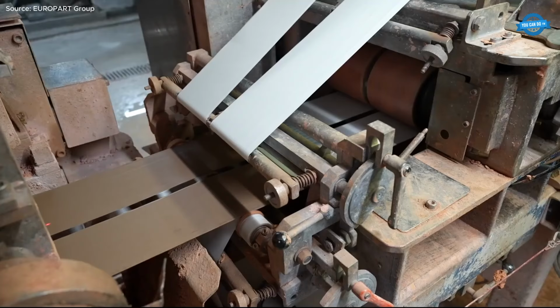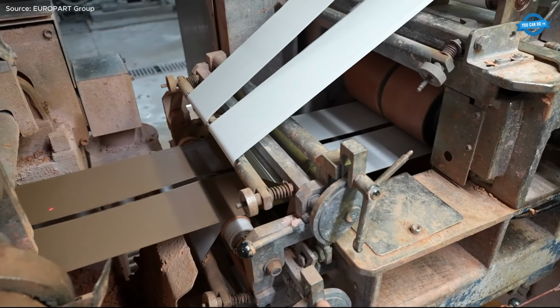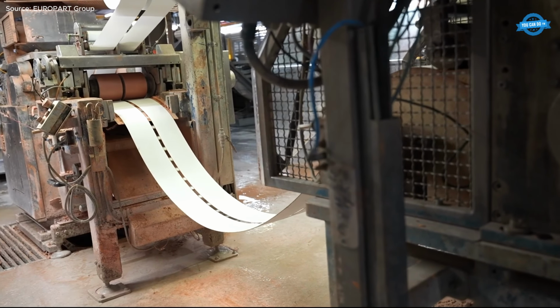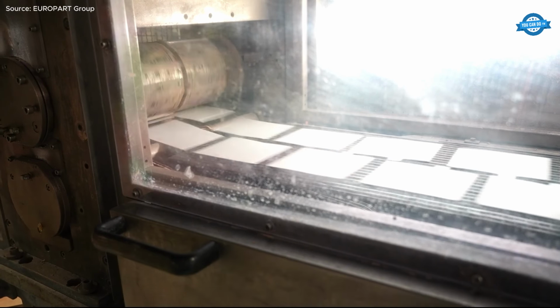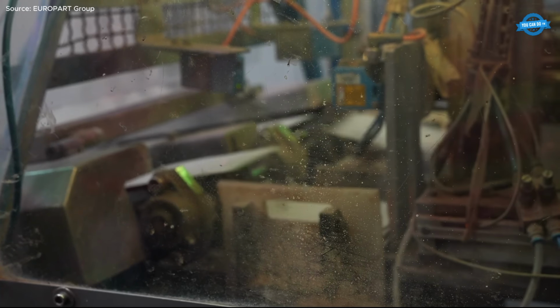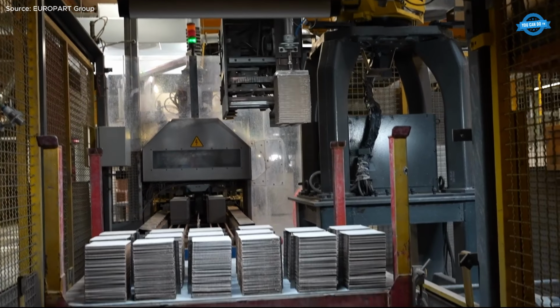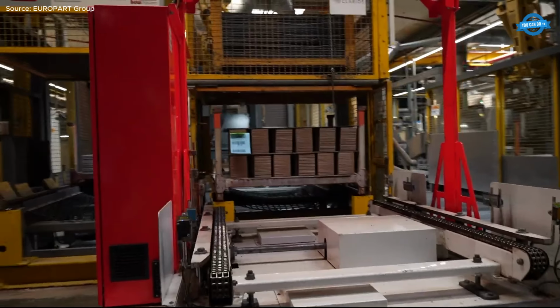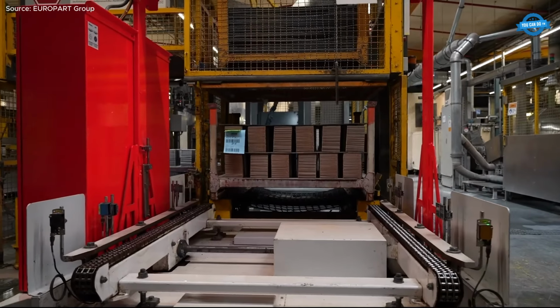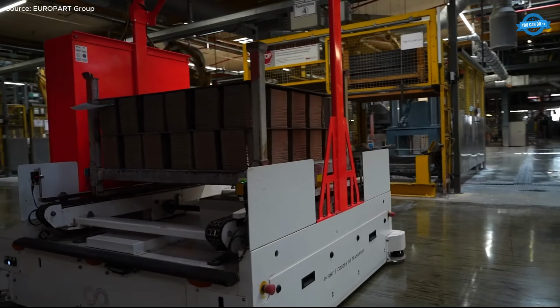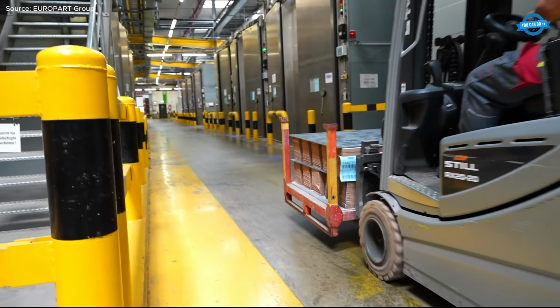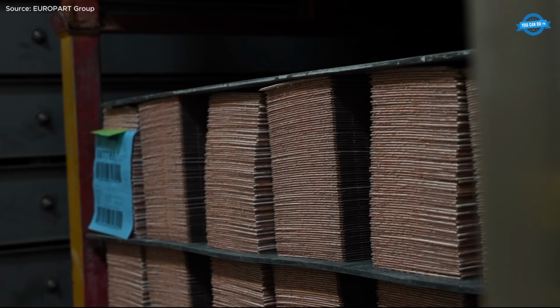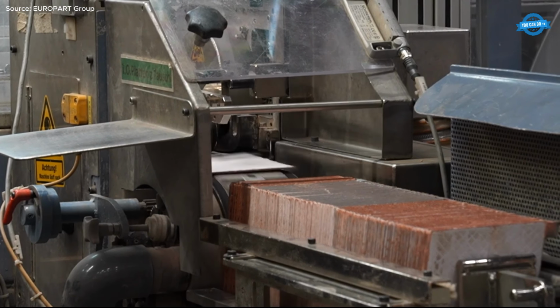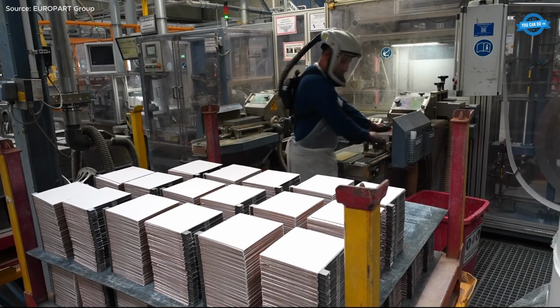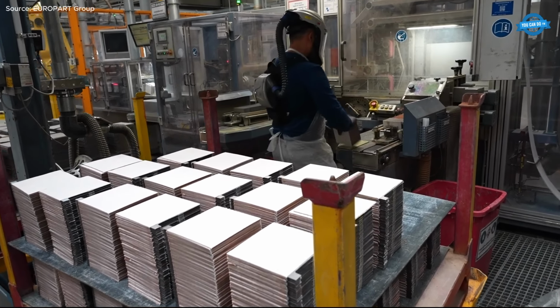In parallel, pure lead is atomized and oxidized in sealed systems to produce lead oxide dust, which is pneumatically transferred to the paste mixing units. Here, positive and negative paste are formulated and applied to the grids before being laminated with fiberglass mats. Approximately 4 million plates are produced daily and undergo controlled curing to stabilize their electrochemical structure, one of the most critical steps in battery performance.